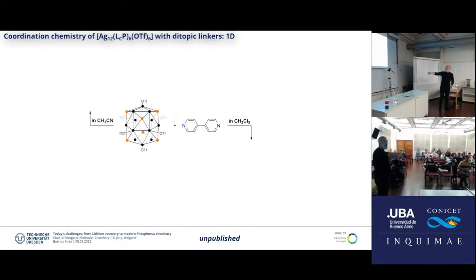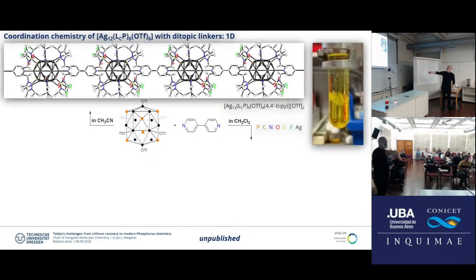Now if you react this one, for example, in acetonitrile or dichloromethane, it depends a little bit on what kind of solvent, polarity, reaction conditions. Again, you get beautiful crystals, and in the case of acetonitrile, we get like one-dimensional strands. Now this is a 1D MOF, with the difference that the linker is not a single atom or a POM, which is being used, it's a metal cluster. In my opinion, I think it's the first example of a metal cluster being used as a node in MOFs.